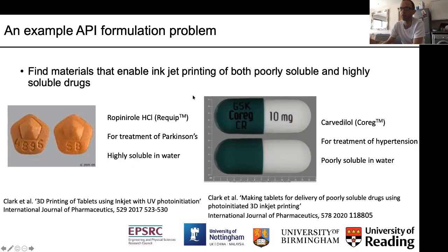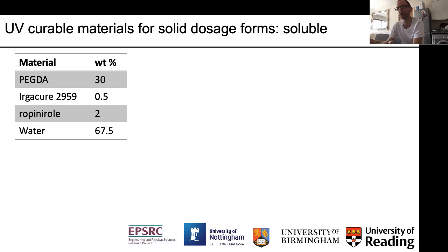So the first one was relatively simple, I would say, though it took a long time for us to be able to formulate this, and led us directly to the idea of going to high throughput methods. But if we think about ropinirole, it's a highly soluble API, it's a highly soluble drug. And we decided to go along a kind of hydrogel type approach to being able to encapsulate that into a printable form. So we created a formulation around polyethylene glycol diacrylate, commonly used as a cross-linker, and we used that in combination with a photoinitiator for UV curing, our drug, and water. So the water is there for essentially two roles: to be able to get the drug into the tablet in the first place, and then of course it allows it to be released once it's ingested.